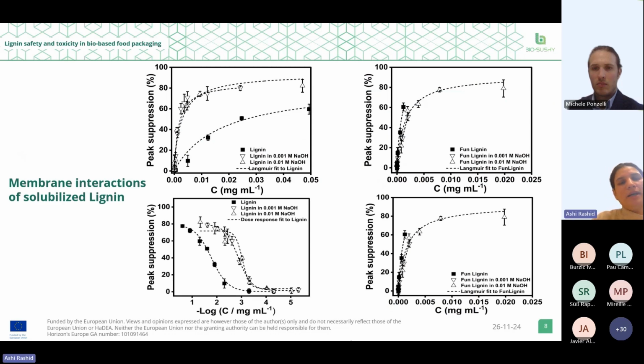For the membrane disruption assessments of the lignin and the functionalized lignin, RCV plots were recorded by subjecting different concentrations of these lignins to the assembled lipid layer in the electrochemical flow cell. Then the percentage peak suppression is measured as a metric from the RCV plots recorded before and after each lignin exposure assay. This percentage peak suppression is the direct estimation of the membrane disruption caused by the membrane active materials, or lignin in this case.